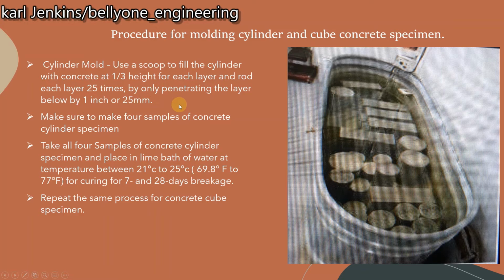Just as I've indicated to you when you're doing your slump test or your air test, you basically just fill the mold to about 1/3. The first layer you rod 25 times right throughout the cross section of the concrete inside the mold, and then you fill the mold again to 2/3 of its height. You rod through the second layer and you only penetrate the first layer by 1 inch. You do the same for the third layer. You put in the third layer, you rod 25 times through your third layer, only penetrating the second layer by 1 inch. So that is basically how you prepare the concrete specimen by molding, just as when you're doing the slump test or the air test. Two, make sure to make 4 samples of the concrete cylinder specimen.